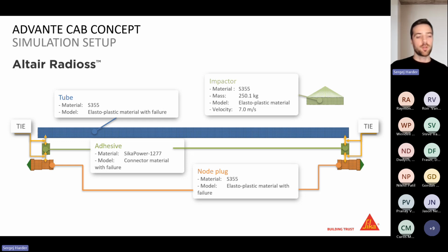So these models still run quite fast, even though you sometimes have these scaling difficulties with the adhesive. The adhesive is quite small compared to the rest of the structure. And with these cohesive zone elements, or in that case, the connector material, you can have a quite coarse mesh and still be able to simulate the behavior of the adhesive. So that's what they're used for.